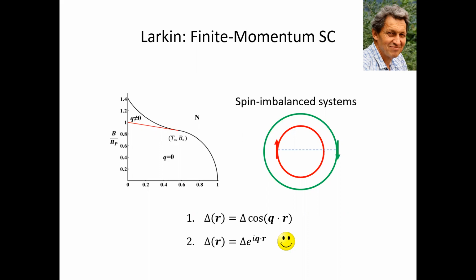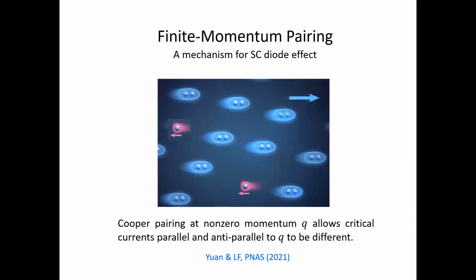On the other hand, I'm going to focus on the second possibility, that the pairing only involves a single wave vector q. In this case, the superconducting order parameter is spatially varying only due to its phase. Its phase changes linearly in space, but the magnitude of the gap stays constant. Okay, so this type of finite momentum pairing seems very intriguing, because the gap function still stays constant in magnitude. And so it's not quite clear how we can detect this kind of pairing. So now I'm going to show that the diode effect could be a very good way to reveal the existence of this kind of single Q finite momentum pairing.